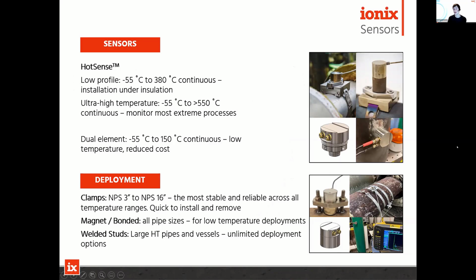The advantage of this probe is it can work through coatings. So it's great for upstream applications and coated pipes, standard epoxy coated pipes, painted pipes, for example. And for these lower temperatures, this probe will also work with a magnetic and epoxy-based coupling system. So there's no need for straps for this probe. It's great if you have a really large pipe or vessel, or you want to install multiple probes in a single circumference. This is the one for the job.